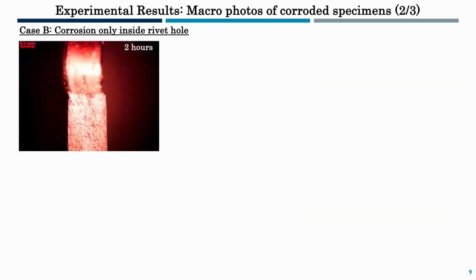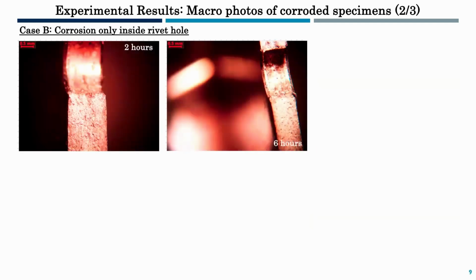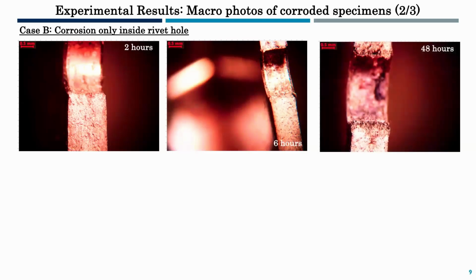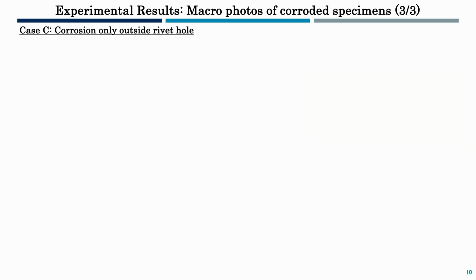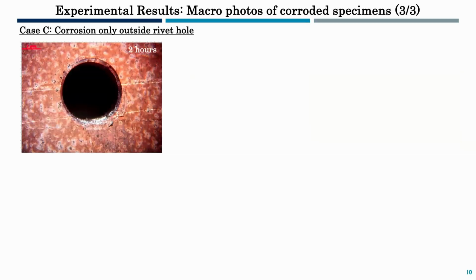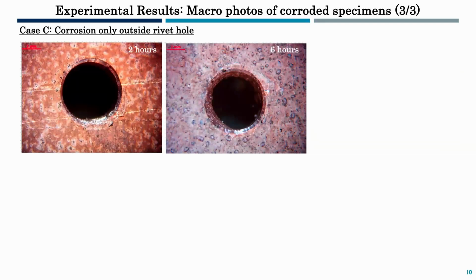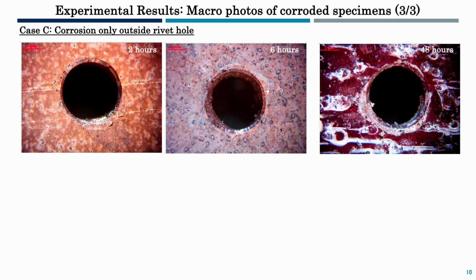In this slide, the results for case B, where only the inside of the rivet hole was corroded. Again, the evolution of corrosion is presented. And as you can see, in the extremely high exposure time, several cracks are noticed. And here are the macro photos for case C, where only the area outside of the rivet hole was corroded.